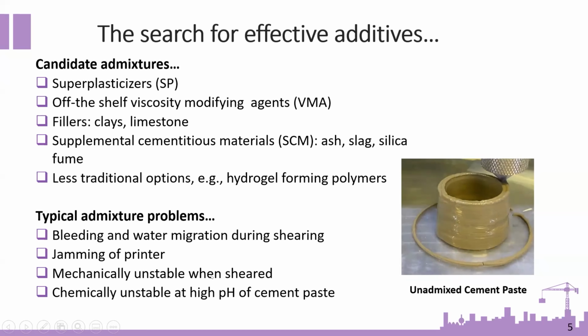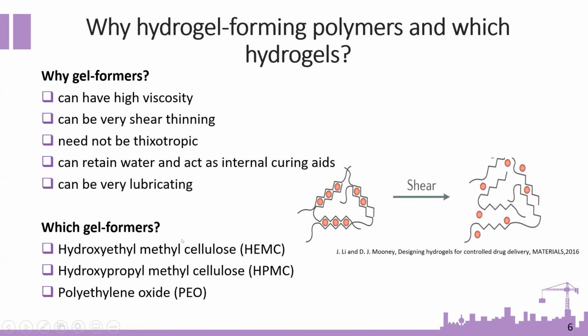We selected hydrogel forming polymers because of their properties, and we decided not to go with traditional admixtures. So which hydrogels, and why hydrogel forming polymers? Because hydrogel forming polymers can have high viscosity. They can be very shear thinning. They don't need to be thixotropic. They can retain water and act as internal curing aids. They can be very lubricating. So hydrogel forming polymers have wonderful properties as candidate materials for producing robust, scalable, printable pastes.